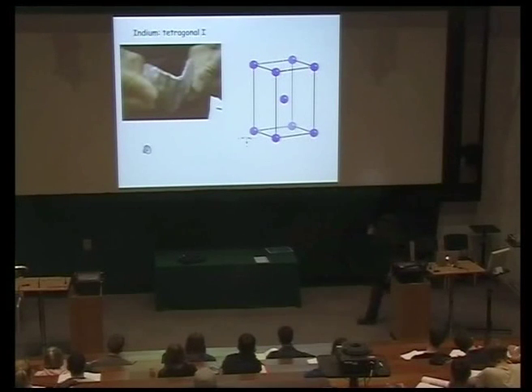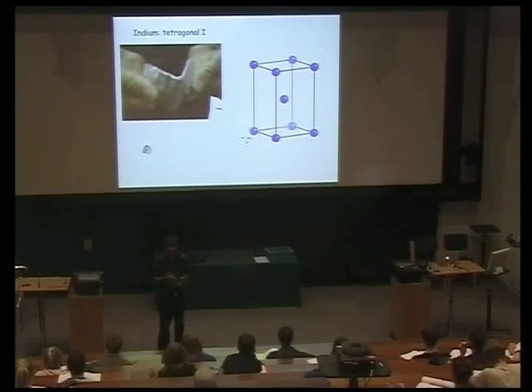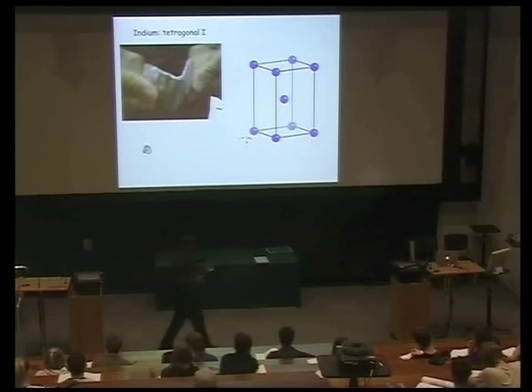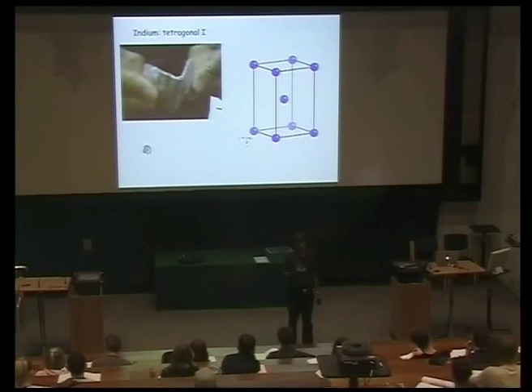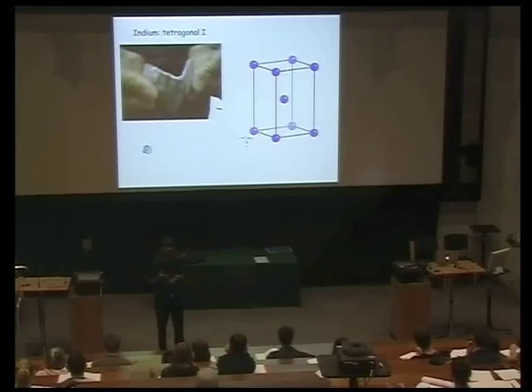I'm going to show you a demonstration where I'm bending a piece of indium, which is a metal. Mechanical twinning doesn't require any diffusion — it's a disciplined movement of atoms — so sometimes we call this a military transformation. They all move in concert, so it can happen extremely rapidly. Just like sometimes we get a latent heat of transformation, you can release that energy by sound emission.